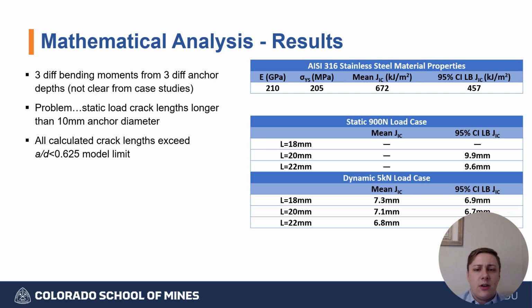So the results of this are where we run into some problems, namely that the critical crack lengths for many of the geometries we examined are actually longer than the 10 millimeter diameter of the anchor bolt, and the remainder are outside of the crack length to diameter ratio, which the Dawood and Cartwright model establishes as valid.